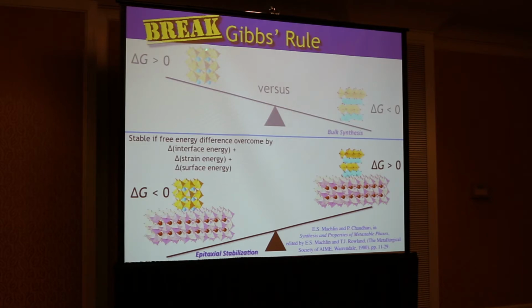But the way that we're stabilizing this phase is to change the system. So the system includes not only the phase that we want, but also the underlying substrate. If you have such a redefined system, and you bias the free energy of this phase by this interface, you can indeed make it so that this is the stable system over that. It allows you, from a synthesis perspective, to still grow this phase quite slowly and grow it with high perfection. What you use as a substrate, though, is key.